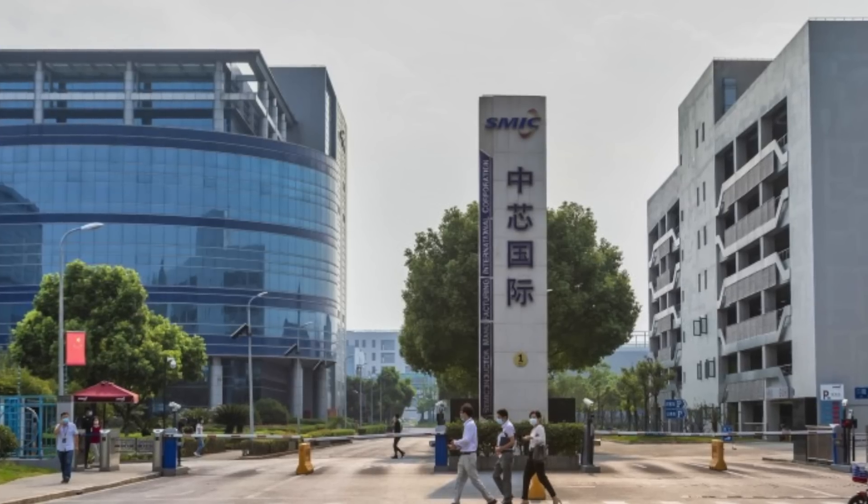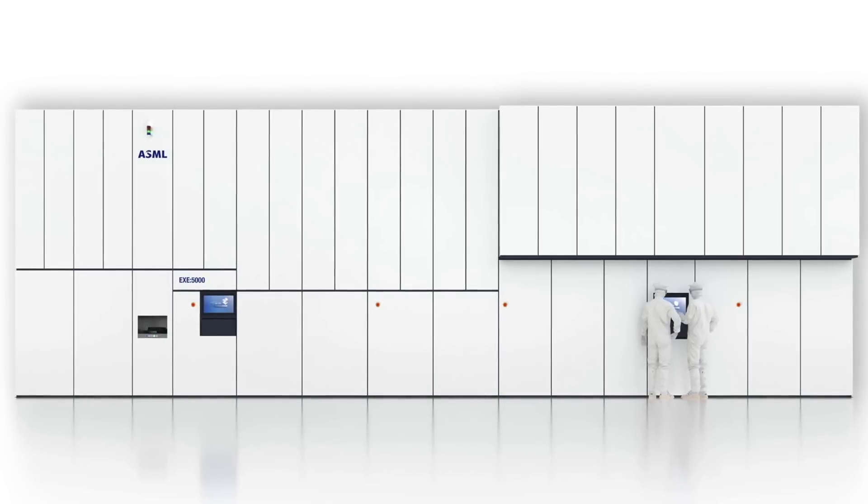Each wafer exposure costs time and money, and I suspect the complexity and costs of SMIC's seven nanometer technology are sky high — nowhere near the same economic efficiency as the same technology from Intel, TSMC, or Samsung Foundry. I've read that it's at least 30 percent cheaper to fabricate seven nanometer technology with EUV compared to DUV tools. As for pushing further with DUV — I think in theory one can use these machines to achieve five nanometers or even smaller via multi-patterning, but production at high quantities will take time and defect rates will be very high.